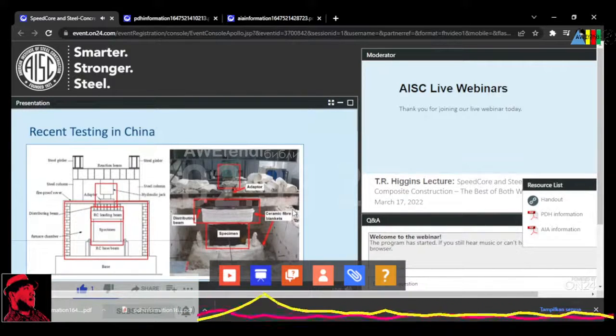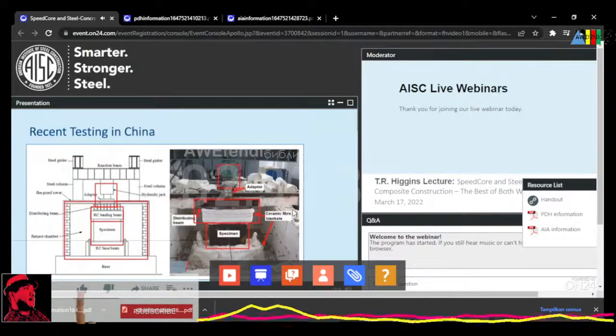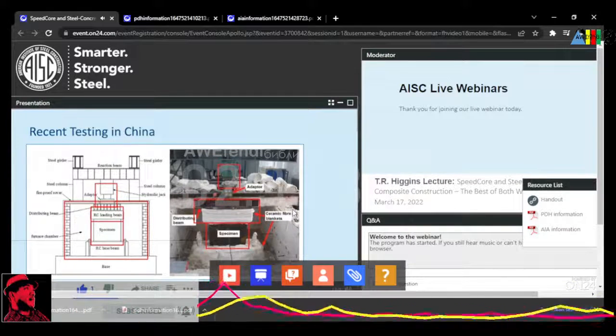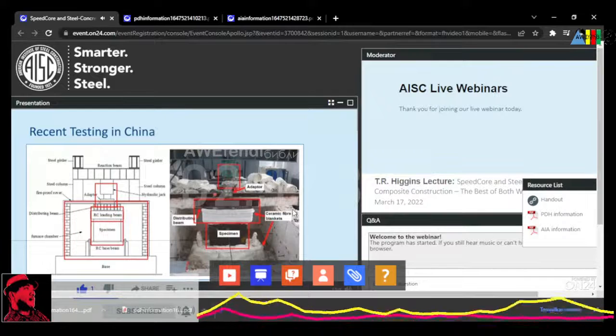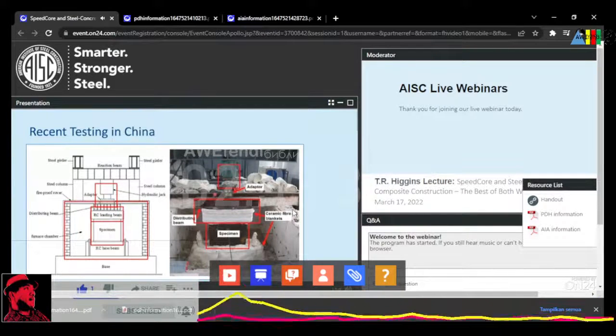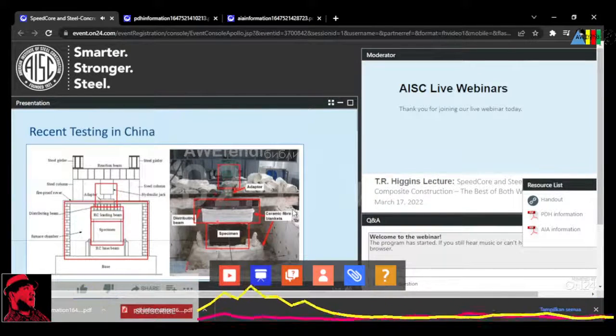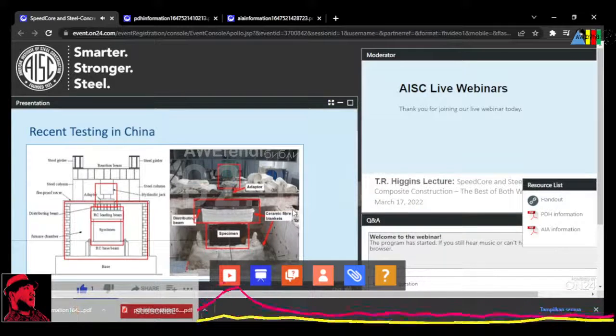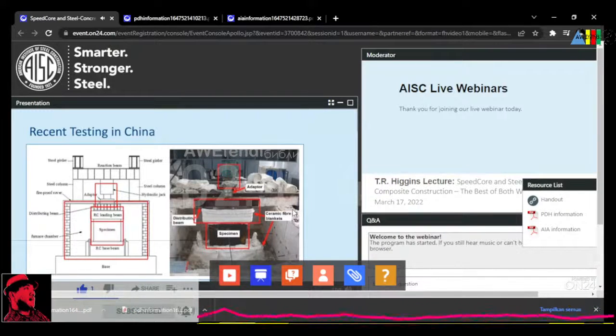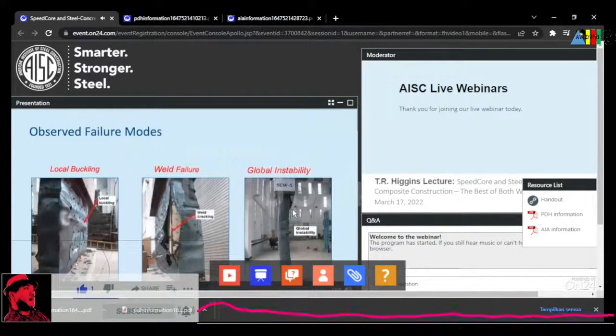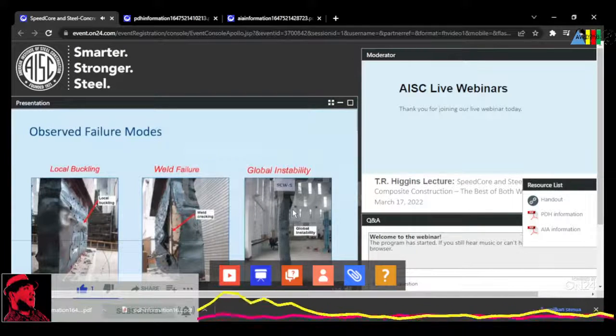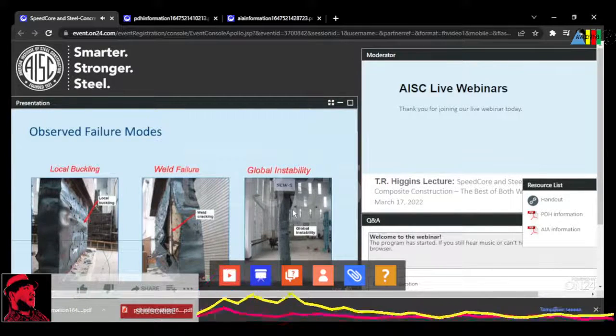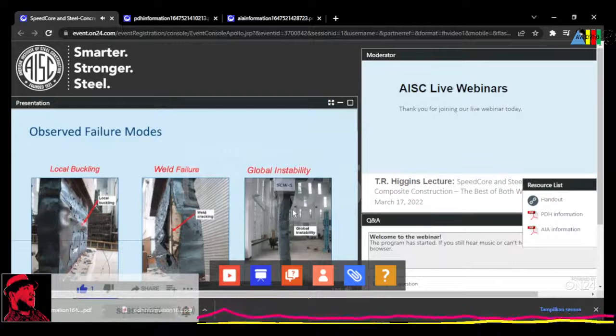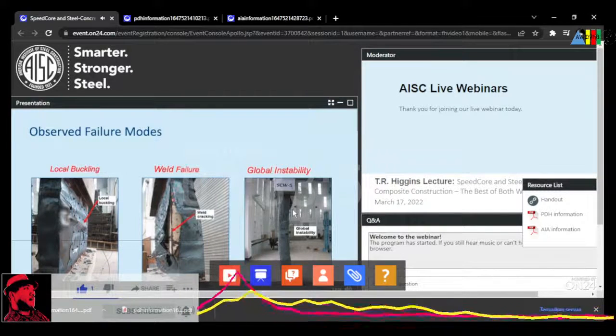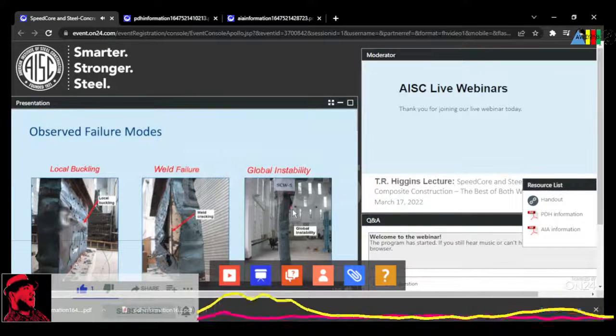There have been a few fire tests around the world on composite walls. This photograph shows some furnace tests that were conducted in China. The composite wall was subjected to gravity loading and the standard fire temperature time curve. Some of the experimentally observed failure modes included local buckling of the steel plates, weld splitting at the corners, and global instability.